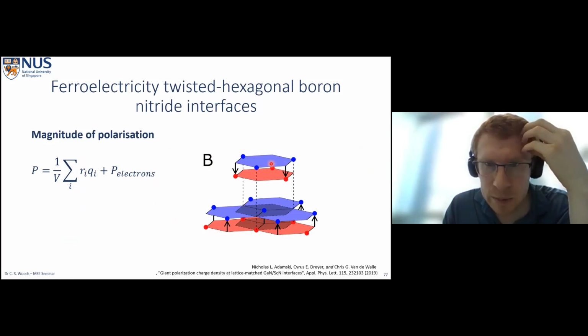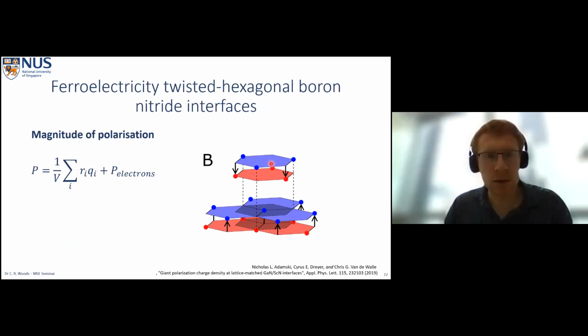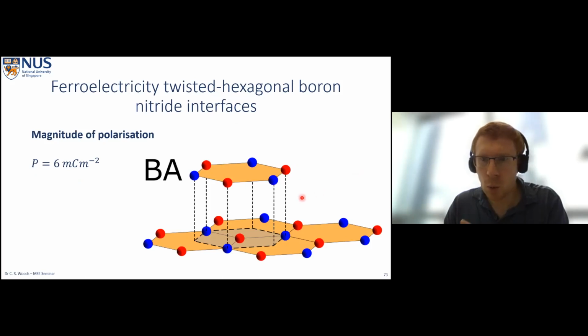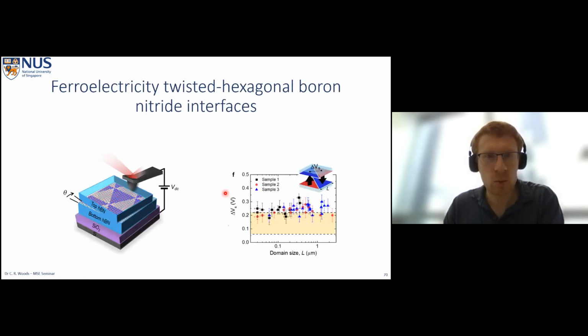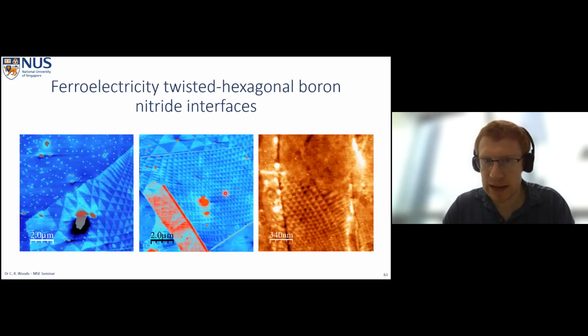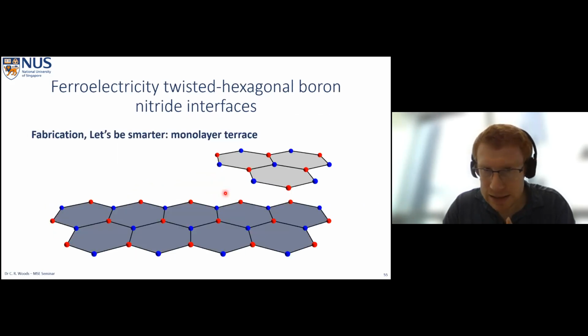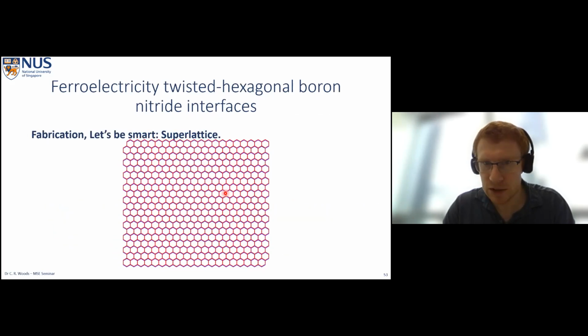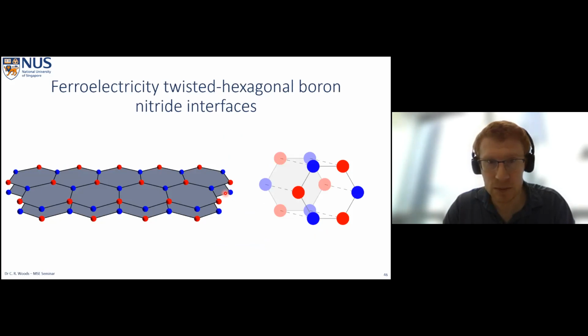Does the polymer contamination affect the formation of the superlattice structure and EFM measurements? Okay, that's a good question. So does polymer contamination affect our measurements? Let's minimize that. Something that I didn't mention while we were doing this talk was that polymer contamination is actually deliberately not a feature of our piezoelectricity measurements.